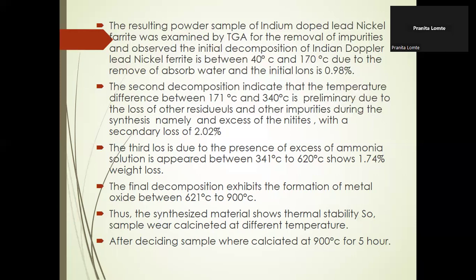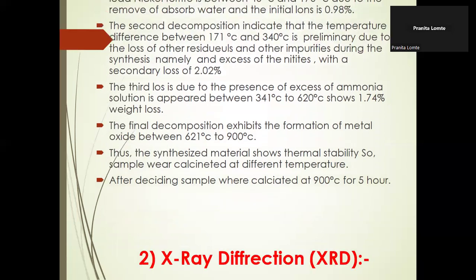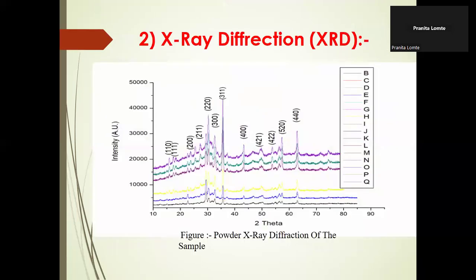The final decomposition exhibits the formation of a metal oxide between 621 degrees Celsius and 900 degrees Celsius. Thus, the synthesized material shows thermal stability. So samples were calcined at different temperatures: 700, 800, and 900 degrees Celsius. After calcination, we decided the sample calcined at 900 degrees Celsius for 5 hours, and then the sample was sent for X-ray diffraction.